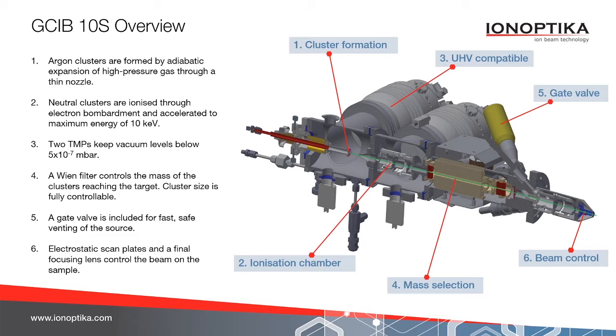Those clusters are then propelled via jet propulsion into the source region, where they are ionized through electron bombardment, and then accelerated to a maximum energy of 10 kilovolts, though that can be varied. The system is fully ultra-high vacuum compatible. Two very large turbomolecular pumps keep vacuum levels in the column below 5 by 10 to the minus 7 millibar. There's also a gate valve, as I mentioned, to protect the chamber from vacuum loss.